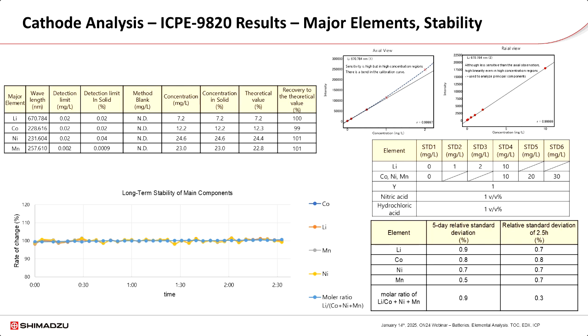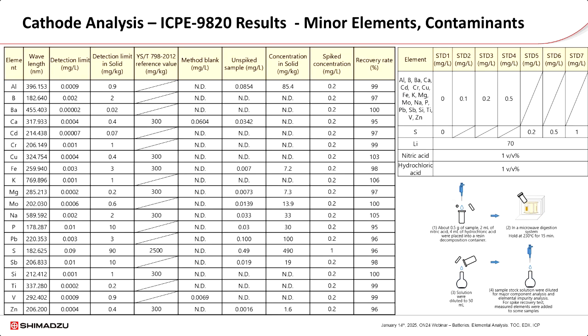Radial view was selected for the major element due to the wide range of linearity and because the abundance of this element did not require ppb level detection limits. Alternatively, axial view was selected for the minor element of cathode material in order to quantify low levels of contamination and other materials present in the solid.